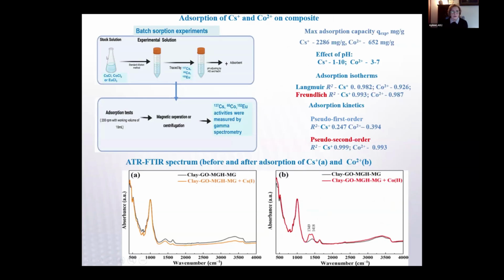So batch sorption experiments were performed. We used solution traced by radioactive isotopes, and samples were measured by gamma spectrometry. Quite high adsorption capacity was obtained. This composite can be used in a wide pH range, and adsorption isotherms indicated good agreement with the Freundlich model, and adsorption kinetics with the pseudo-second-order model.